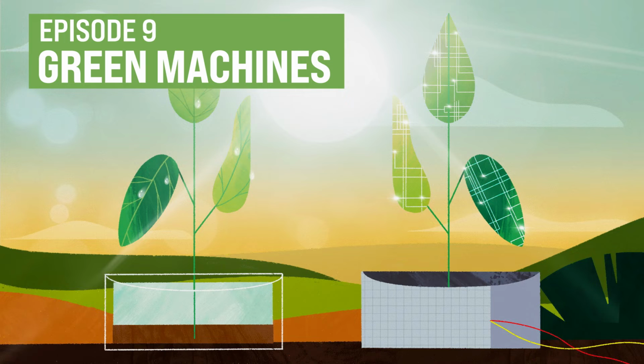So the idea is to choose various band gaps that are matched to the spectrum of the light coming from the sun, which has many photons in the visible area that we can see, but also has photons that are in the ultraviolet. We can't see those, and also ones that are in the infrared. We also can't see those, but we might want to use the energy from them in our artificial system. So we use semiconductors that are sensitive to different parts of the spectrum from the sun in order to try to harvest them all if we can.